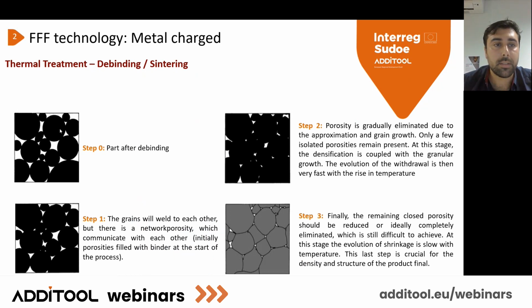So the part after debinding, we have the grains of metal. Step one, we increase the temperature. We start to weld to each other. We reduce the porosity. Step two, the same, and finally we have the sintered part with some closed porosity because we sinter at atmospheric pressure. We don't have any pushing on the sintering. Instead of classic sintering of powder with force from outside, with a 3D print machine you will have a lot of different geometries, and it's not possible to have a pressure in the sintering. We can have the HIP that we have tested. I will explain before, but you cannot have an external mechanical force because you have a lot of different geometries.